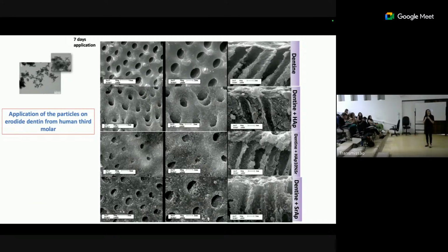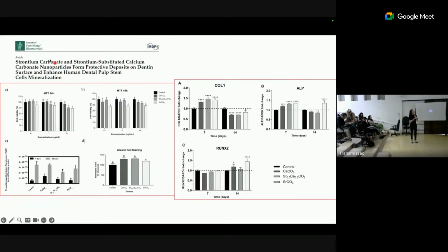to use a compound with lower solubility and with a higher affinity for the surface of dentin. And why not try to imitate the mineral structure that we already have in the dentin? So that's what we did here. We also used strontium carbonate nanoparticles to try to block dentin and favor the deposition at the dentin surface. And we also treated human dental pulp stem cells with these particles, and we saw that the strontium carbonate particles were able to enhance the differentiation of the stem cells in a mineralizing phenotype.